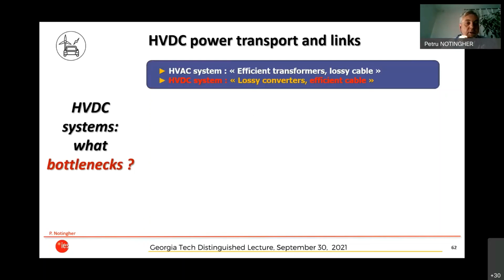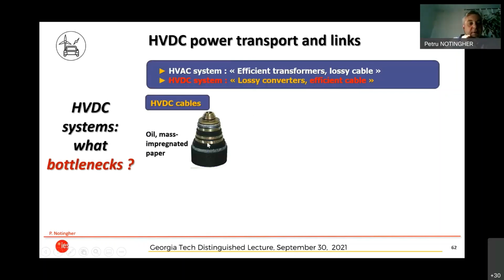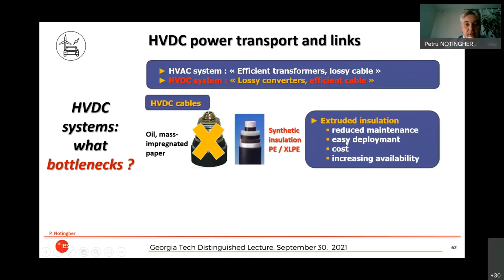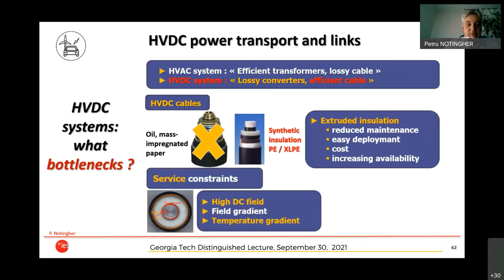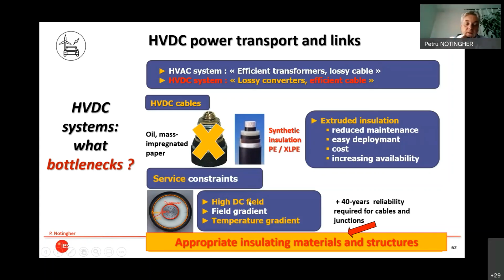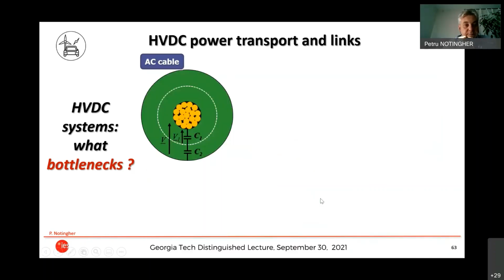So why are these systems not so widespread? Because there is a bottleneck, and the bottleneck is the cable. So oil and mass impregnated paper cables have been used, but there are problems relating to maintenance, and the synthetic extruded insulation needs to fulfill all these requirements. And the problem is that the service constraints, which are a high DC field, a field gradient, and a temperature gradient, and the reliability constraints make it so that we do not have enough appropriate insulating materials and structures. So we need materials to fulfill these constraints.